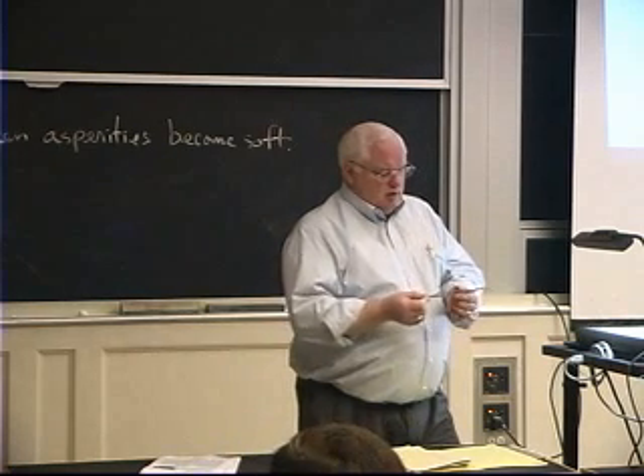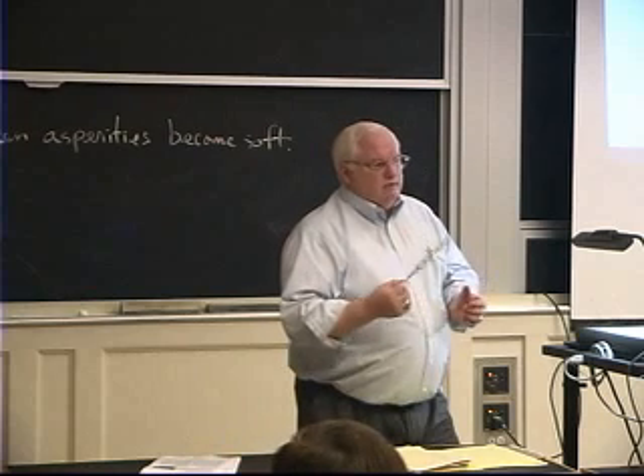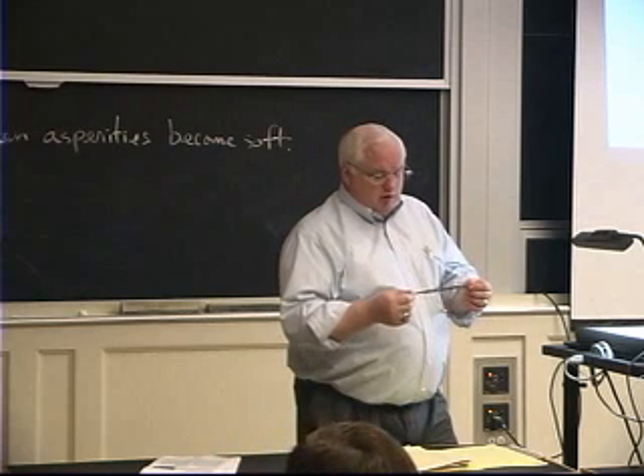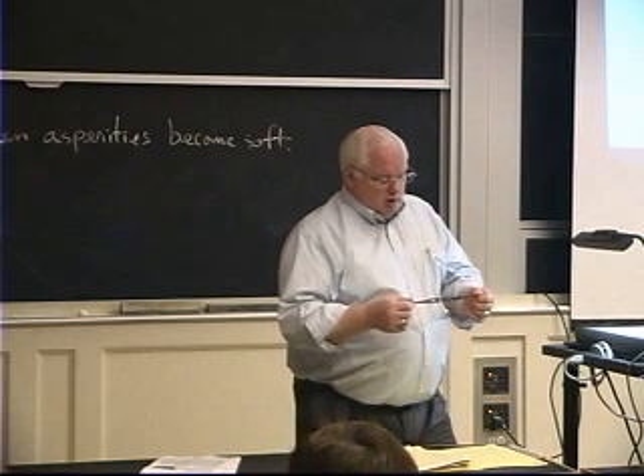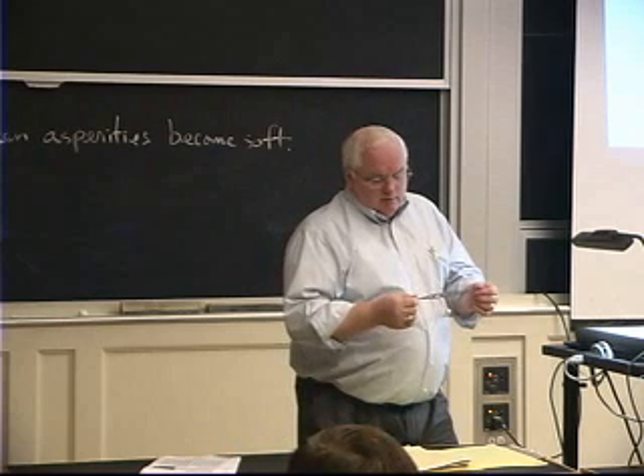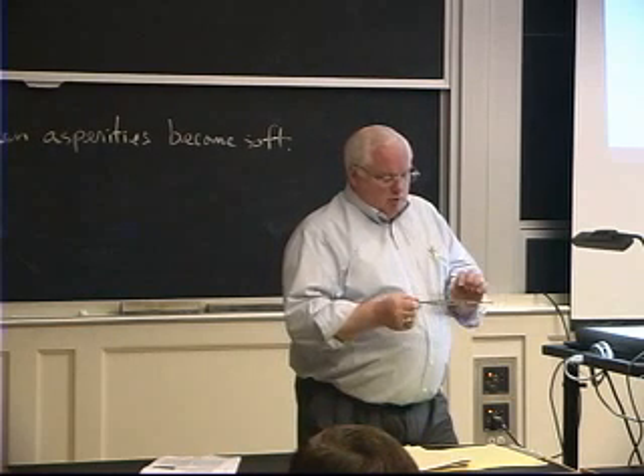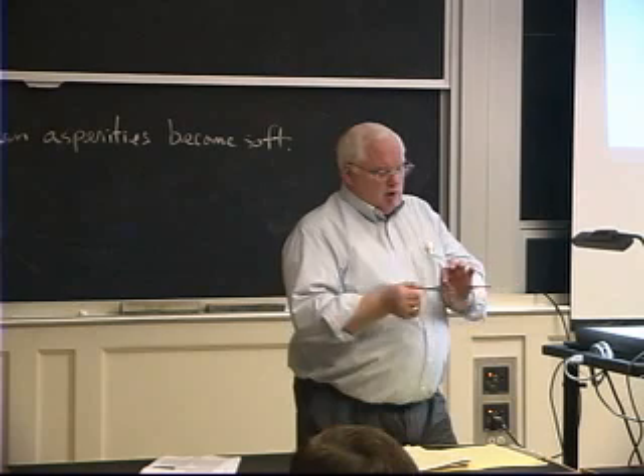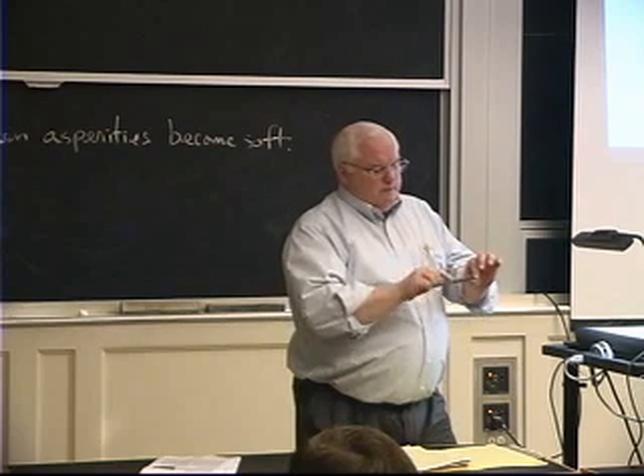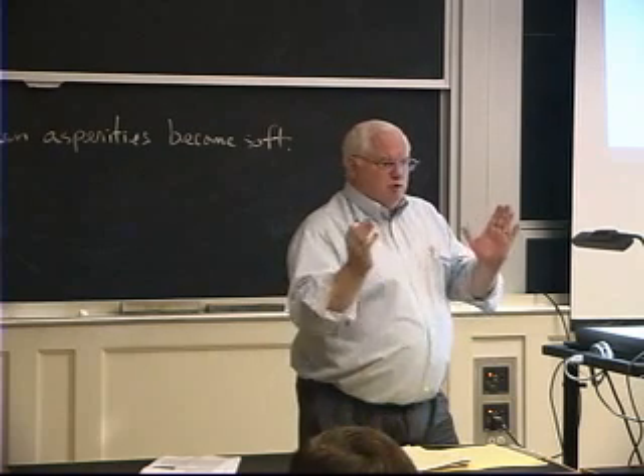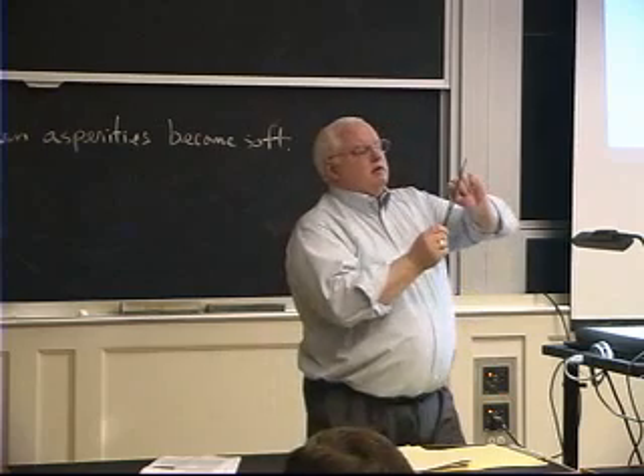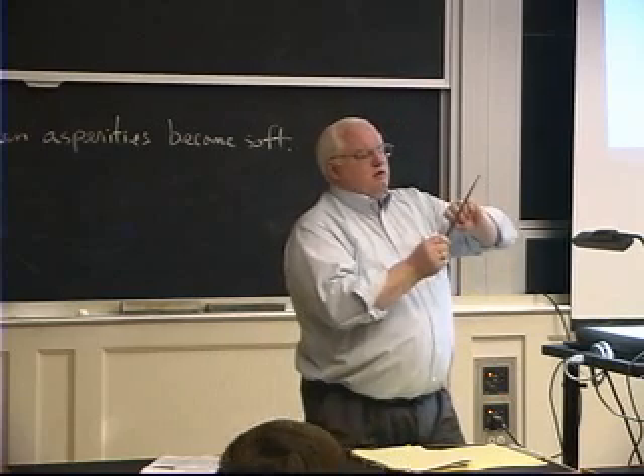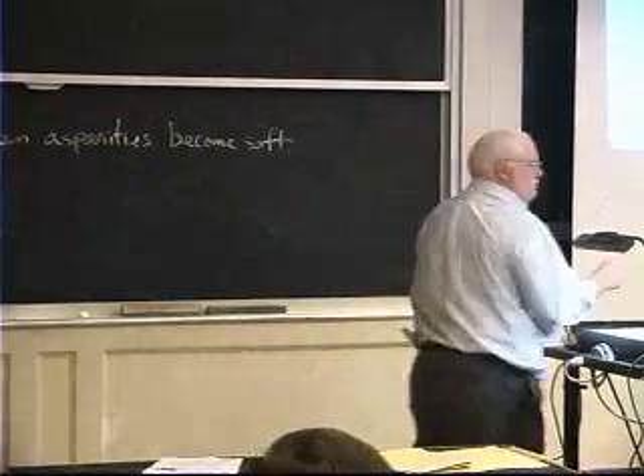What I've got here is actually a prototype for a diffusion bonding specimen for one of the airfoils for the inlet of the F-22 fighter. This was given to me by a student who had worked at Pratt & Whitney. He decided I could use it more than he could. But basically, they took two titanium plates, shaped them, and then diffusion bonded them together. So this is like putting two pieces of bread together. And at these intersections here, if you look at it, it was kind of sharp notched machine because you basically have put these two together and diffusion bonded the titanium under heat and pressure.